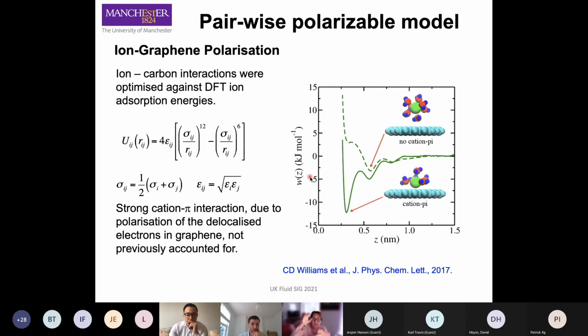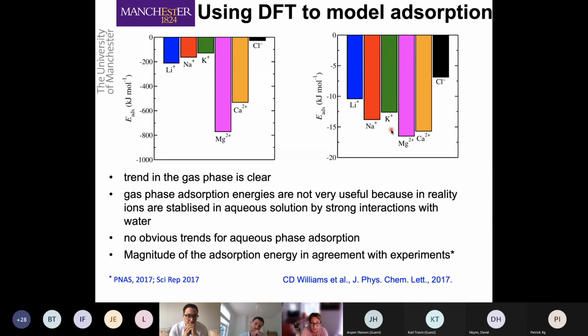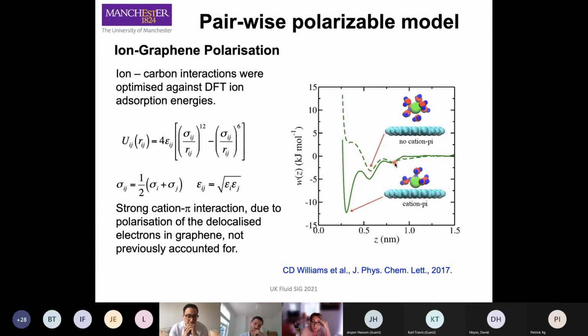We put an ion in the water, explicit water in the molecular dynamics, and we slowly pulled the ions towards the surface of the graphene. And then we kept on changing the value of the epsilon between the carbon and the ions until the minimum in the potential of mean force, which is this thing here, was matching the value that we were obtaining from the DFT calculation. So, for example, this is the potential of mean force obtained with the original force field, which was an OPLS, where basically there is no polarization effect, and indeed there is a repulsion of the ions because the PMF is positive. The solid line corresponds to the PMF with the modified version of the epsilon, where we basically optimized just this value down here. We don't know what happens in the middle here.